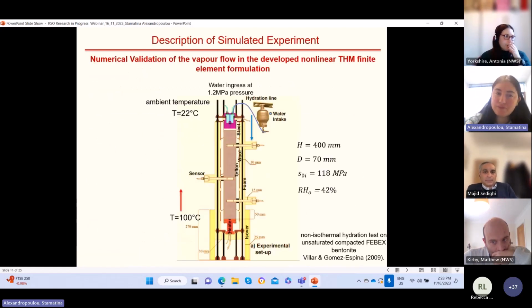Next, I will present one of the simulations that I performed during my PhD project. This is a numerical validation of the vapor flow in the developed nonlinear THM finite element formulation. As we can see, we have a cylinder. In the middle of the cylinder, in brown color, is the bentonite material, which has this height, this diameter, this initial suction and initial relative humidity. Across the cylinder there are sensors that measure relative humidity and temperature, and the experiment applies a temperature gradient by heating the bottom of the cylinder, while the top of the cylinder remains stable at an ambient temperature of 22 degrees Celsius.